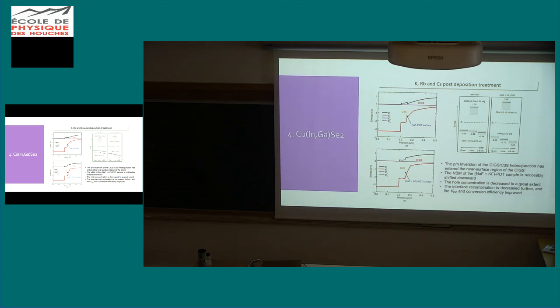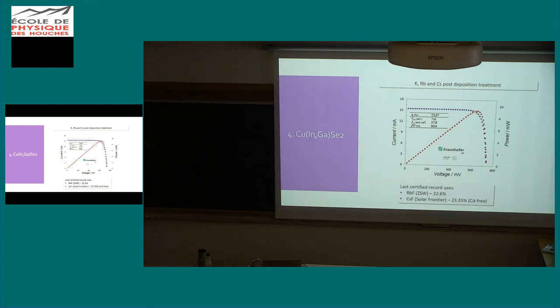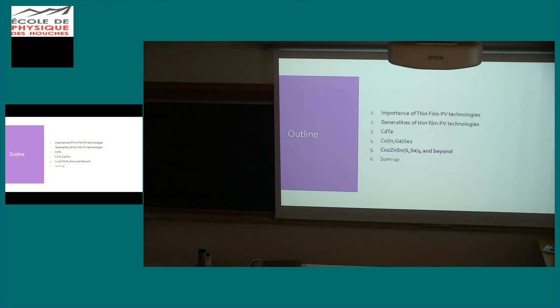But it's extremely complex and people are still debating about what happens, because it seems that potassium, rubidium and cesium are also forming compounds like potassium indium selenide or rubidium indium selenide that can really play a role in that. But this is a very important step if you are working on CIGS in order to get efficiencies over 20%. And this is one of the latest records presented, over 22% efficiency. Although the record right now is 23.3% by Solar Frontier.